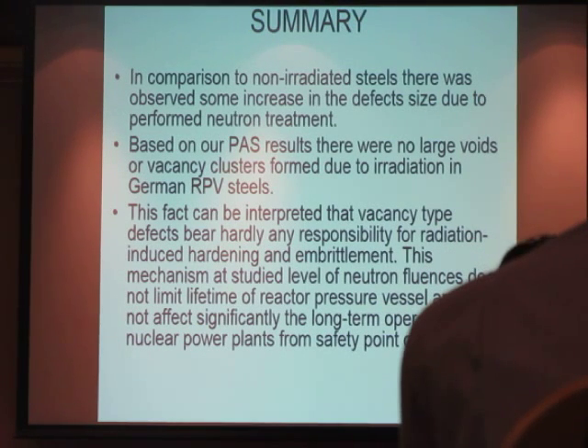Summary. In comparison to not irradiated steels, some increase in the defect size was observed due to the performed neutron treatment. Based on our PAS results, there were no large voids or vacancy clusters formed due to irradiation in German RPV steels. It's a very important message, because if we were to identify larger defects like voids, the hardening and embrittlement would be much higher, and it would not be possible to allow the operation of the nuclear power plant anymore.